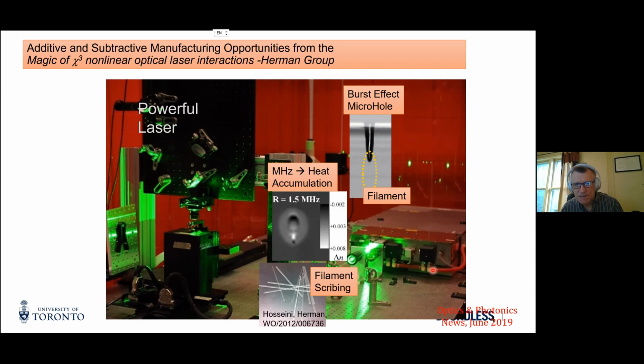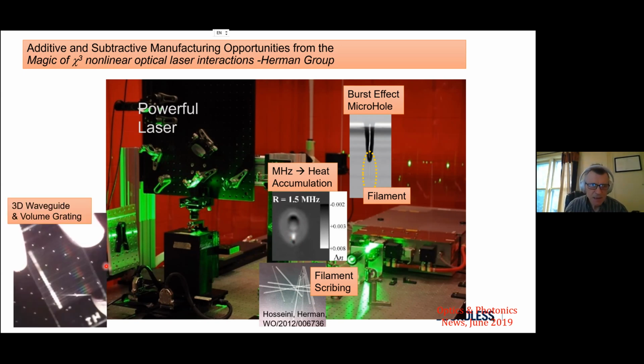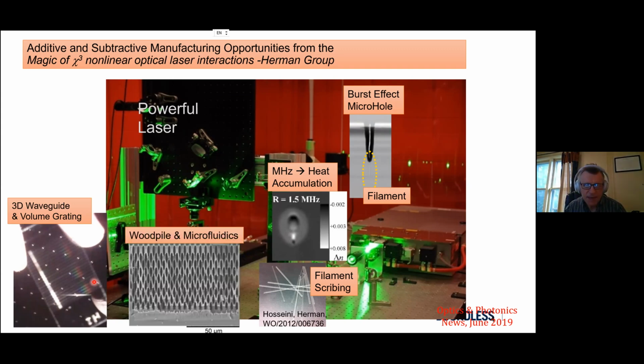This heat accumulation effect is what helps us in making low loss waveguides. This is a laser interaction zone down here, and this is the heat accumulation zone. And around here, this is a positive index change. So many groups today are making waveguides, even commercially now is beginning. You can modulate while you're writing. These are grating waveguides, right? Grating. So we're going to talk about that. And this is a woodpile structure. It's actually a cross section of a microfluidic channel, but where we've etched an inverted woodpile structure of holes by using chemical etching through laser tracks.